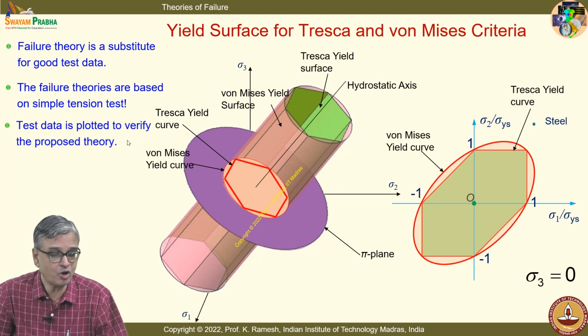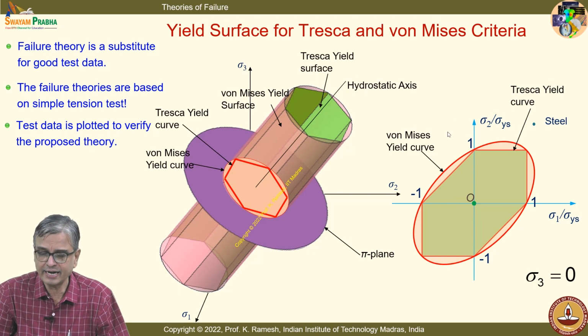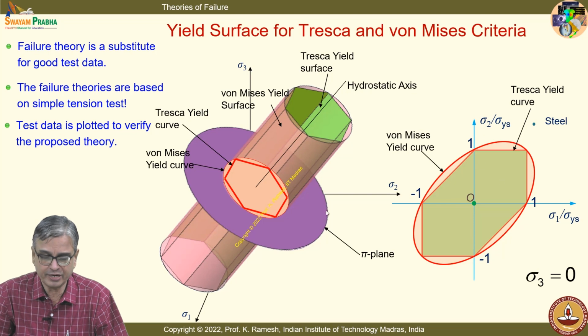Test data is plotted to verify the proposed theory, and I have also slightly modified it because the test data is reported like this. They put it like sigma 1 by sigma ys, but the shape remains the same. You have steel, and I have steel data like this. So, it is lying between Tresca and von Mises, and at one or two places it has slightly exceeded.